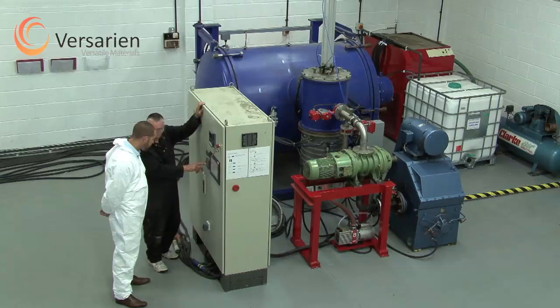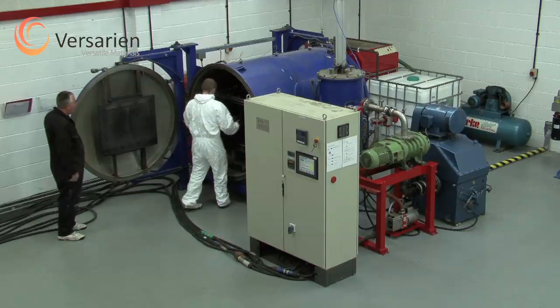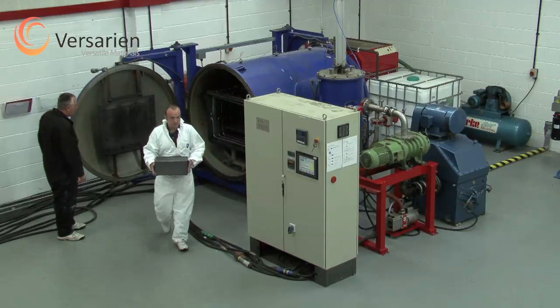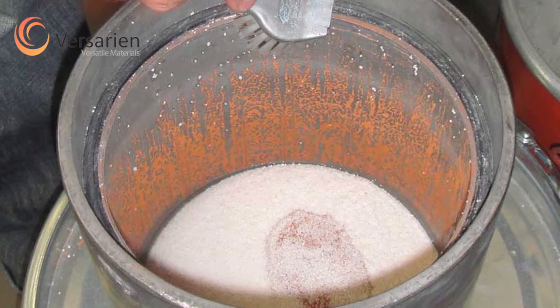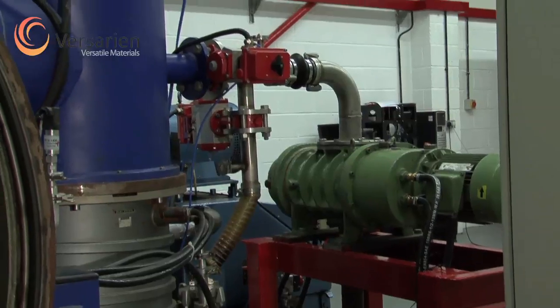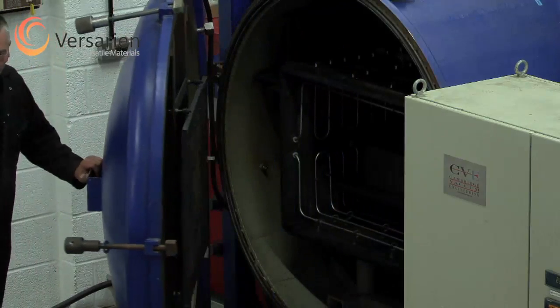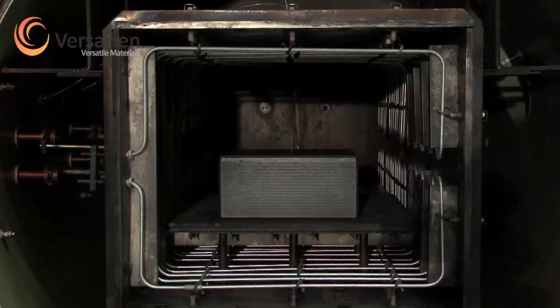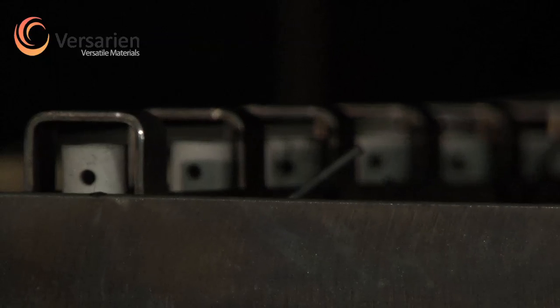The basic principle on which the construction process is founded is the mixing of metal particles with soluble non-metal particles. The manufacturing process employed by Versarien Limited consists of powder mixing, where copper particles are mixed together with non-metal particles; compaction, where this mixture is compacted to net and near net shape forms; and heat treatment, where the mixture is exposed to temperatures of around 1000 degrees Celsius within a vacuum. By applying extreme levels of heat, it is possible to make the metal particles adhere to one another without melting. The non-metal particles are then decomposed or dissolved away.